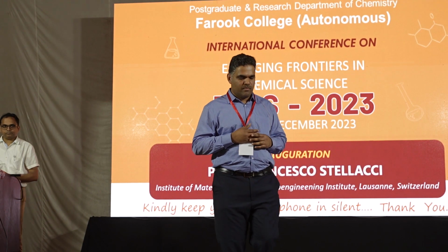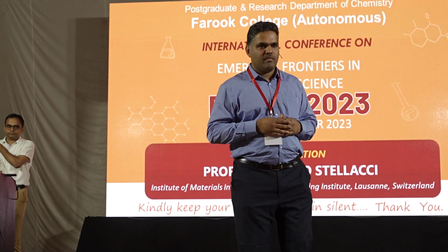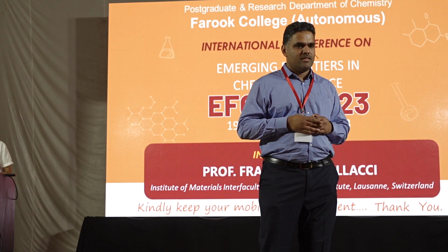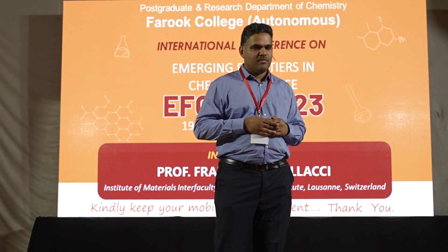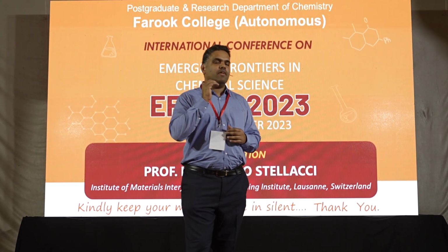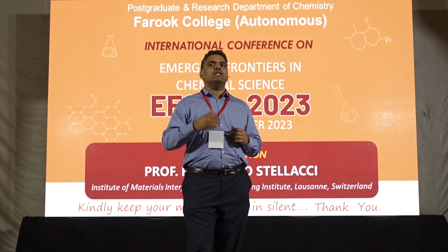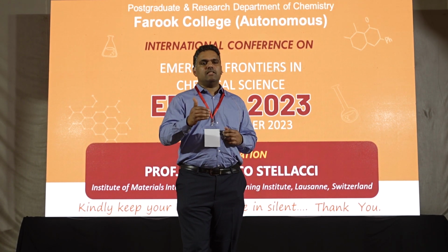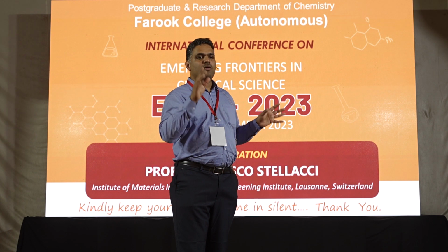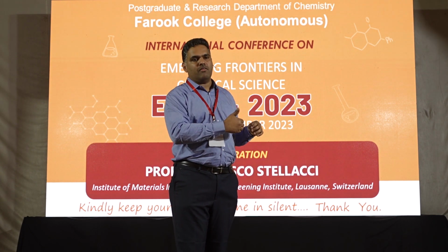Thank you. One related question. In the mechanism that you were talking about, there was a movie. When the separation is really small and things start moving, is it possible to see ordering of water? Again, we don't have any experimental evidence, only modeling in the dynamic case, but the movement is fast, which suggests that there is an ordering. If the water is disordered, the same thing could happen with alcohol. But for alcohol, the rate of permeation is 1,000 times less than water. The only reason I can imagine is that alcohol molecules are bigger.